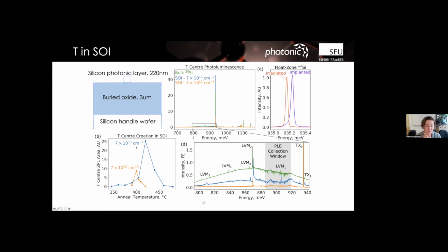That implant flux is actually rather high. We're talking about a couple hundred nanometers of silicon. That's a lot of damage in a very small space. But again, we could see the structure is the same. It's the brightest thing. These materials are just incredibly bright. And the inhomogeneous line width of the material, actually, so it's shifted. Here we implanted carbon-13, so you expect the shift, which is great. But the line width wasn't so much bigger. So the broader strain sensitivity is relatively low. And that's encouraging, because the thing that, as I kept getting into, makes or breaks this technology is really going to be its photonic interface.